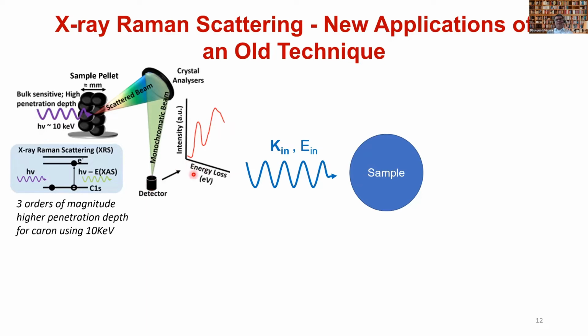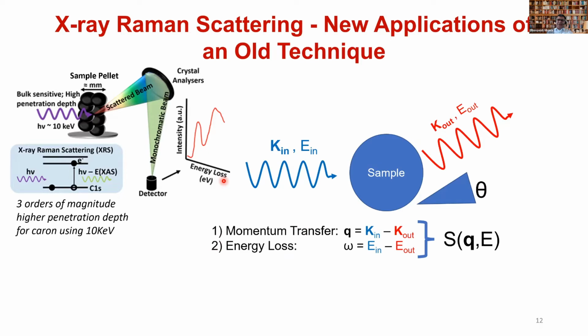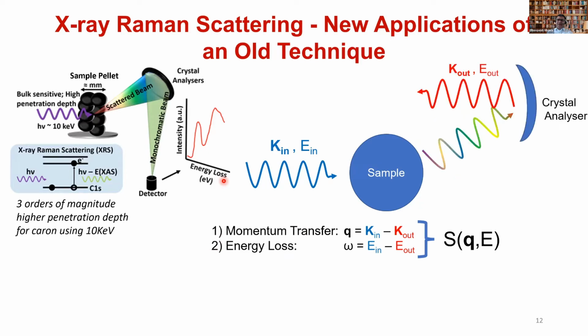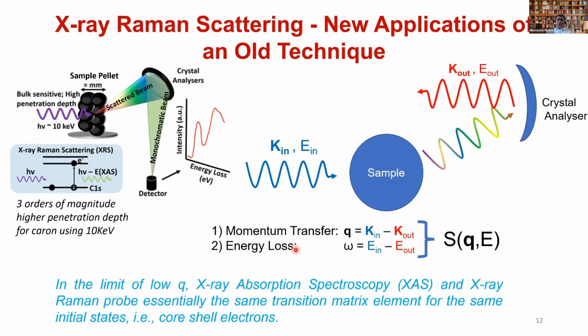And what you plot is basically an energy loss spectrum. This energy loss spectrum is very similar to what you would have for NEXAFS. And again, this is how the schematic works. And in the approximation of low Q, as in low momentum transfer, you get the same information that you'd get for NEXAFS. Now, why only low Q? Because you can use the dipole approximation at low Q. However,